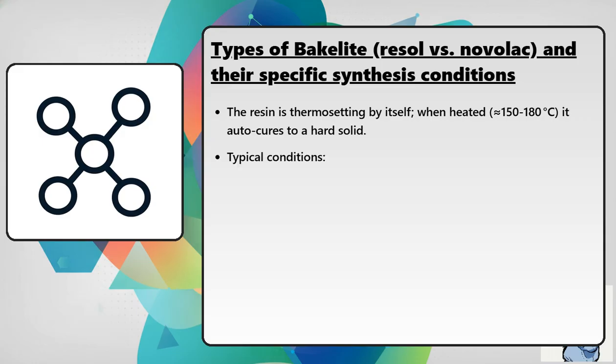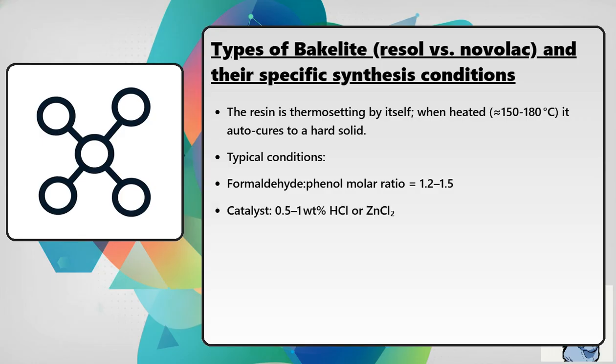Typical conditions: formaldehyde to phenol molar ratio equals 1.2 to 1.5. Catalyst half to 1 weight % hydrochloric acid or zinc chloride. Temperature 90 to 120 degrees Celsius for the reaction, then 150 to 180 degrees Celsius for curing.